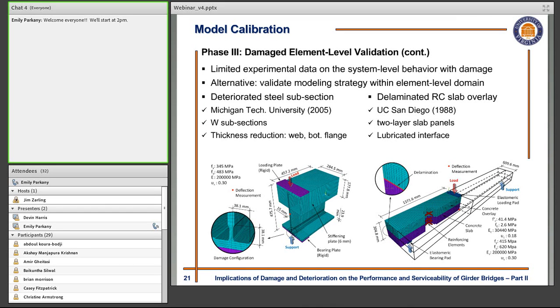Again, similar to the case that we had in phase 1, in order to take advantage of the symmetry in geometry and loading, we only modeled a quarter of this specific slab. In order to simulate the contact area or the interface between these two layers, we used contact elements from ANSYS that are able to transfer the compressive stresses between these two layers, and they are free against the tensile stresses.